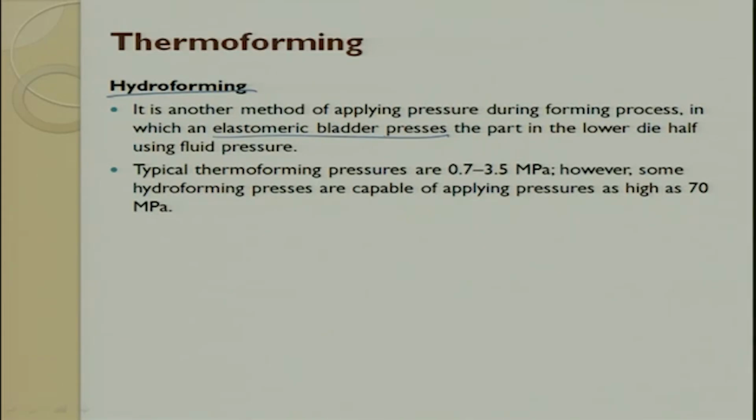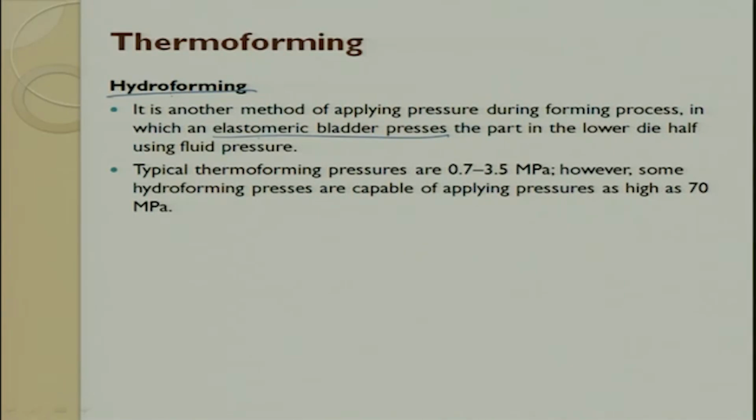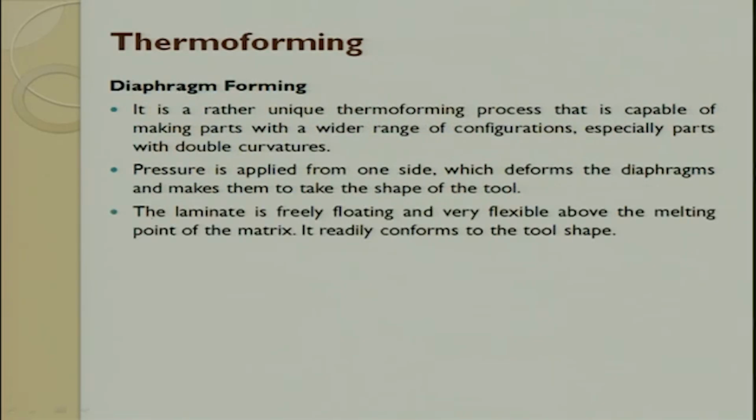Here the pressure is applied through hydroforming, in which we take an elastomer, fill it with water or any fluid at high pressure, and then try to get a consolidation. So, what is the big advantage? You get a much better surface quality output, but you should be very careful about hydroforming, maintaining the pressures. The pressures typically are up to 3.5 megapascal, and it can go up to 70 megapascal for various applications.